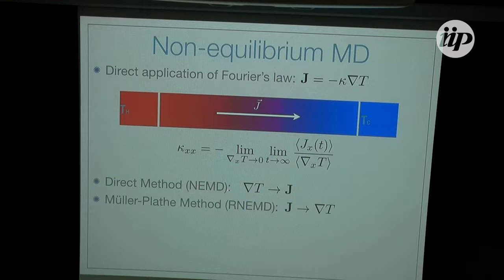One of them is the so-called direct method. I connect a thermostat here and another one here. It can be a Nose-Hoover thermostat, it can be a Langevin thermostat, it can even be a velocity rescaling type of thermostat. It doesn't really matter that much if I use the parameters correctly, which is not that trivial, but the general idea is I put some energy in the system here, and I take out the same amount of energy here. So that amount of energy is flowing through the system. Knowing the cross-sectional area here, and the amount of time, I can calculate this heat current.